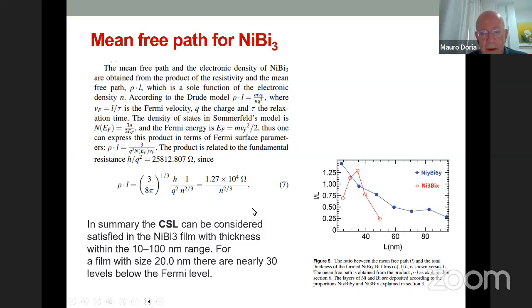This is a nice relation to keep in mind, because if you know the resistivity, you know the mean free path. And then you can compare the ratio between L, the mean free path, and the thickness of the film. And we want this to be much larger than 1, right? We want the mean free path larger than the thickness, so that there are no collisions. Because if you have collisions, you cannot use models like a string. The electron is like a string, so you want the ratio to be much larger than 1.